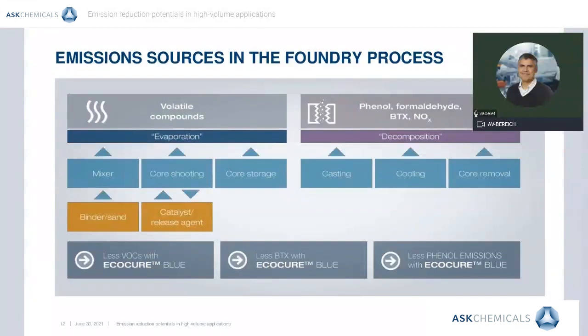To understand where the emissions come from throughout the foundry process, we have created this small diagram. You can clearly see here two types of emission. During the mixing, shooting, and storage of the cores, the emissions come from the evaporation of the lighter products. It can be the volatile solvents, but also amine and release agents. Whereas during the casting process, the binder in the core is burned. There are evaporation phenomena, complete combustion, and forced combustion without oxygen, also called pyrolysis, where the most dangerous pollutants are produced. For example, BTX and NOx.